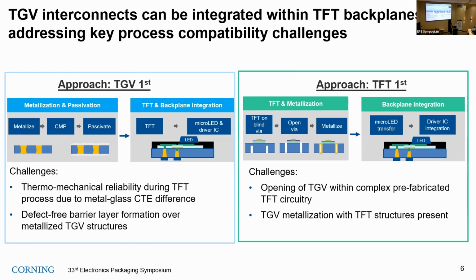And then you fabricate the TFT backplane on it, either LTPS or oxide TFTs. Since you have only a blind via, there is no metal involved, so you don't see any reliability challenges there. Then after you fabricate the LTPS, you open up the via with Corning's proprietary process. Then after opening, we metallize the via conformally, which connects with the TFT backplane. This metal can also be accessed from the B side of the substrate, which is connected to the IC driver board. So I'm going to show some of the results of this TFT first approach in this presentation.